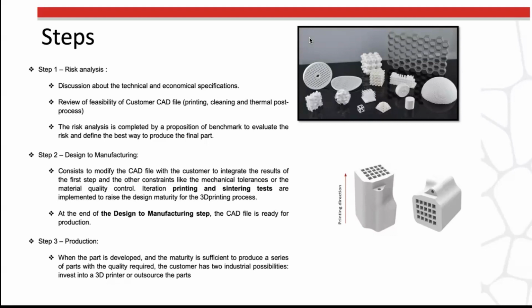I said that we use the slurry. Slurry is composed of a mix of ceramic powder and photosensitive binder. So for SLA technology we use rather high-loaded slurries, with more than 55% in volume of ceramic powder. It means that we reduce the shrinkage, but we still have shrinkage, which is common to any shaping method of ceramics. So this shrinkage makes some challenges that we have to deal with.